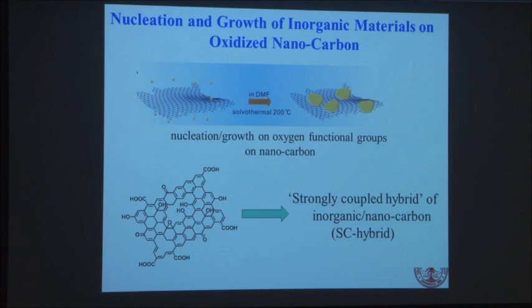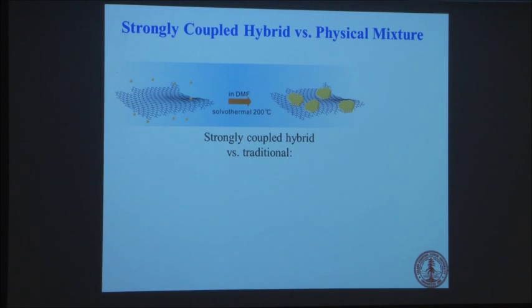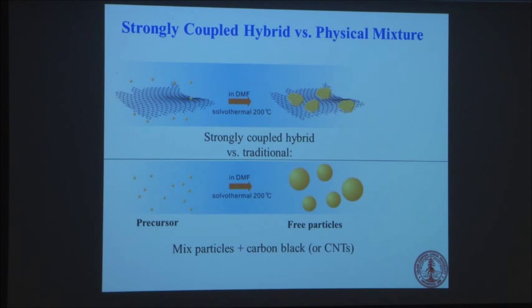And we believe it's actually useful for energy storage or catalysis because this is our strongly coupled system versus this more traditional way in which you make your particle. Okay, a lot of people would make a battery material, for example, and then mix them with carbon, right? So you need a carbon anyway. But in our case, ours is right on top of a sheet. And the electron transport between the particle and the sheet is very easy. So you get electrons in and out very quickly. So you can charge and discharge very quickly, because that's really the idea. And it turns out to work quite well.